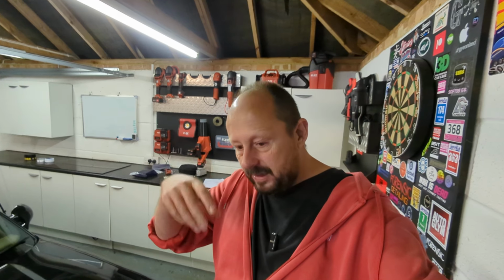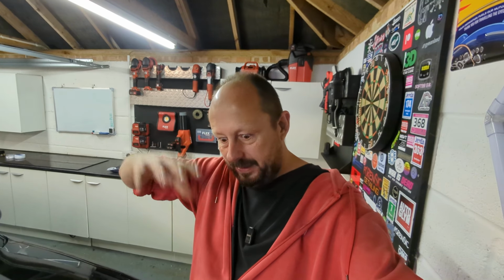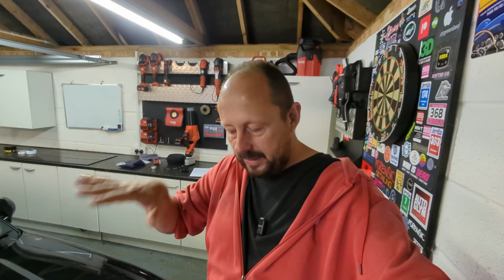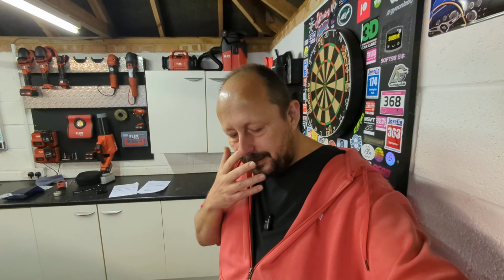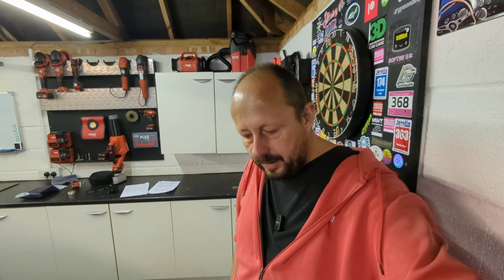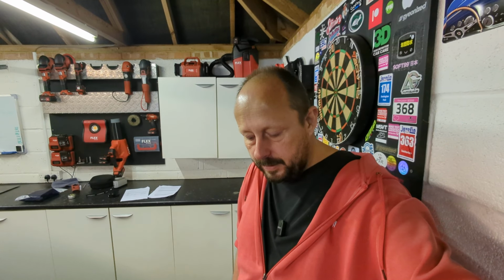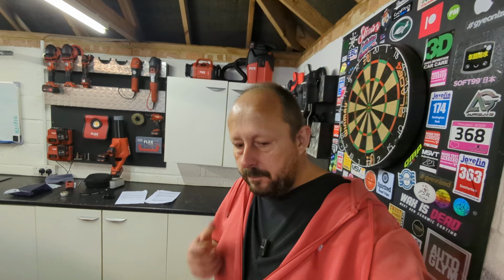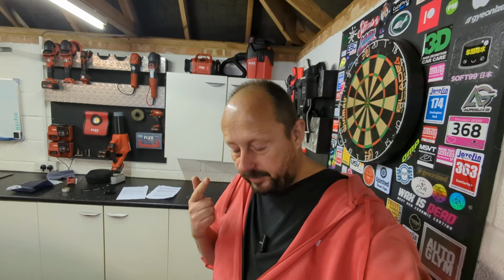When you take the lid off the bottle, the ether disappears, and then it leaves the core resin exposed to the elements, to the moisture, to the air, the hydrogen and the oxygen. So when you spread it in a film, that ether evaporates very quickly and exposes the core resin. That resin then undergoes a state change into a silicon and oxygen based film, and it's a very hard film, and the surface characteristics of that core resin were self-cleaning, dirt release. So it was initially developed to put on building facades, coil coatings, spraying on train carriages for anti-graffiti applications.